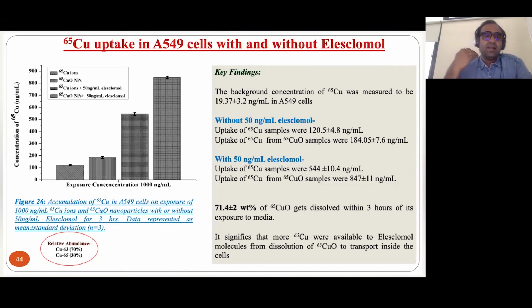But when we combine these copper oxide or copper ions with Elesclomol, we are actually seeing a very significant jump. That is because this Elesclomol is acting as a bus, ferrying copper from outside the cell to inside the cells. And this ferrying is happening maximum in the case of copper 65 oxide nanoparticles. So this is just an example where what we are saying is that by changing the design of a nanocarrier, you can actually minimize the requirement of drug and have a maximum effect on the killing of the cell. So this is an example towards utilizing our nanomaterials for a biomedical application.